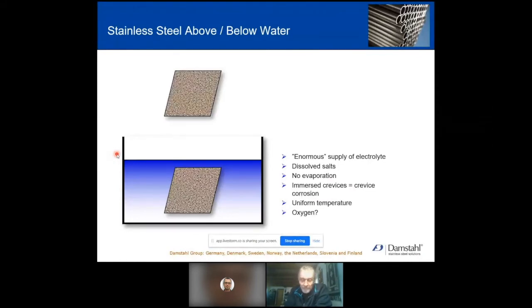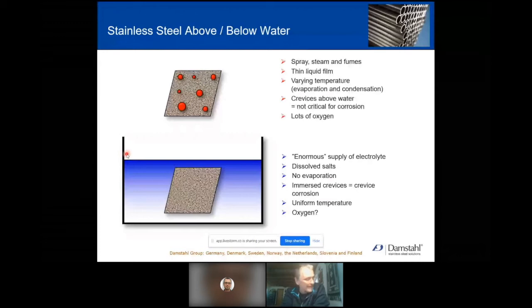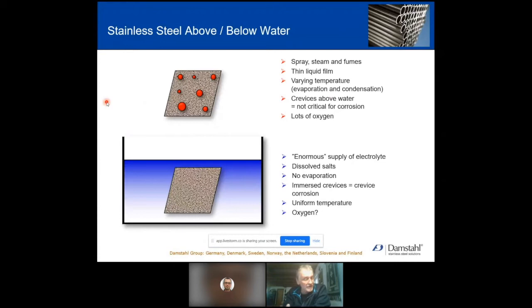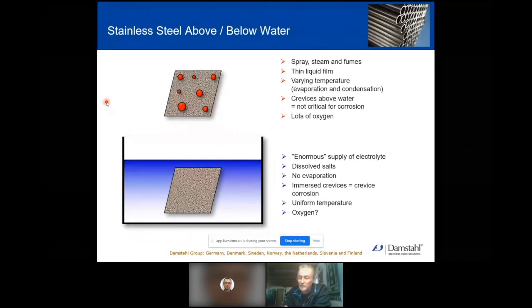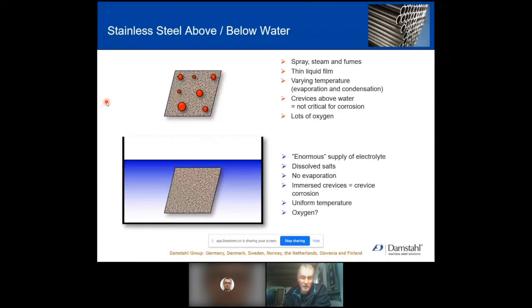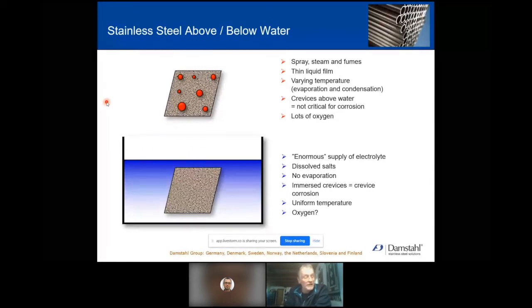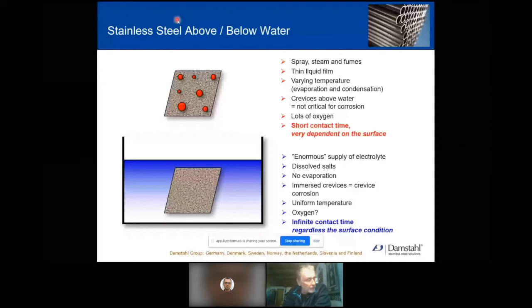What about above water? Yeah, at the most, we have some splash, some steam, some fumes. Maybe we only have a very thin liquid film. We don't quite know the temperature. Sometimes we do, sometimes we don't. But if it's equipment standing on the outside, then we'll have some seasonal variations. Even within 24 hours of the day, we'll have some differences. And then we have a lot of oxygen. And then perhaps the most important difference is that below water, we have an infinite surface contact, which is regardless of the surface condition. And above water, it's very, very dependent on the surface condition.